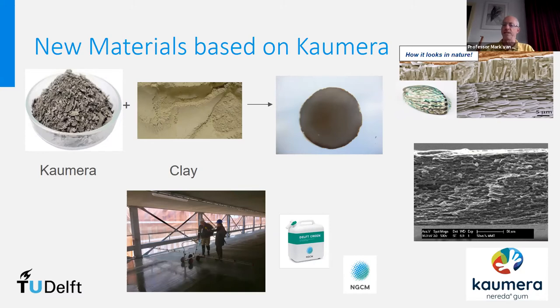And one of the first applications of this kind of composite materials is in coatings. Because if you have this high amount of inorganics, you can make a coating on, in this case, cement, which really closes off the cement. And if you make constructions like buildings, after pouring the cement, it needs to remain moist for about a month in order to get good fixation of the calcium carbonates, which means that either you have to spray water on it all the time during that month or regularly, or you can coat it with it.